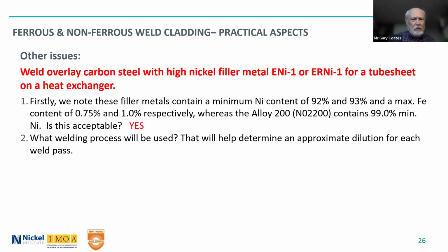So I'm going to take an example of a nickel alloy overlay on a tube sheet. They wanted a pure nickel. They're going to use nickel 200 or alloy 200 for, let's say, the tubes. You want the tube sheet to have that weld overlay on it, and so you use either the ENi-1 or the ERNi-1, which is really the filler metal that you use for welding the nickel alloy 200 there. The filler metals contain less nickel, 92 to 93%, than the wrought material. But again, if you were welding alloy 200 to itself, you'd be using these things. So obviously this is acceptable.